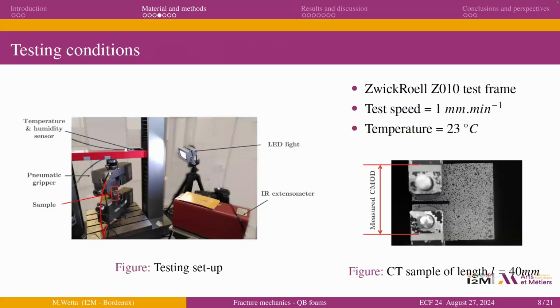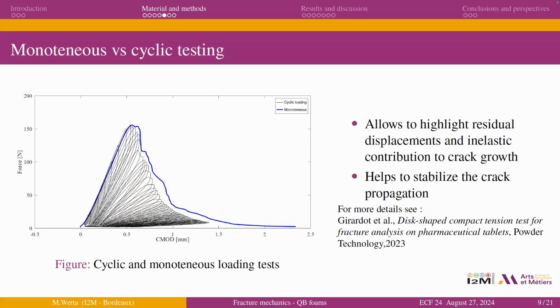So in this study, we have used a classical compact tension specimen, which is about 40 millimeters in length, at room temperature, using a classical tensile testing machine in quasi-static regime. So it's very, very classical for this kind of study.